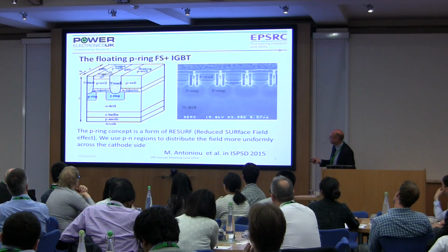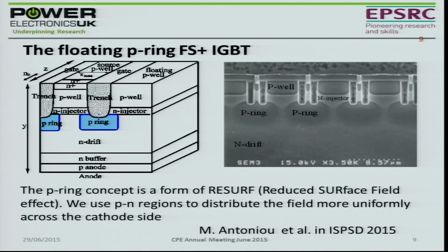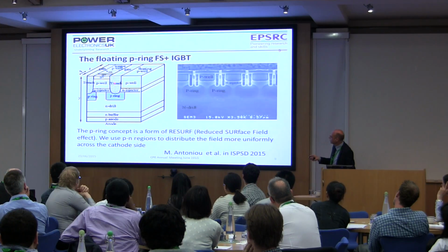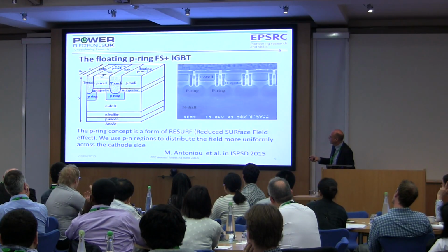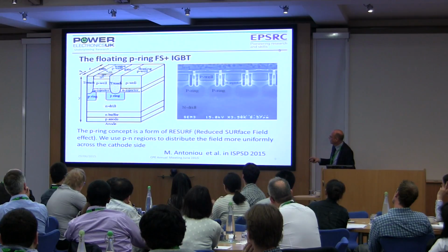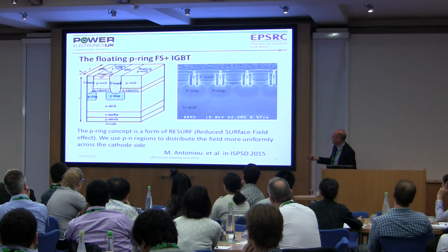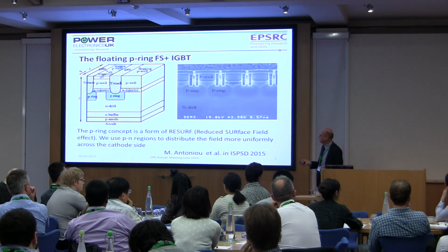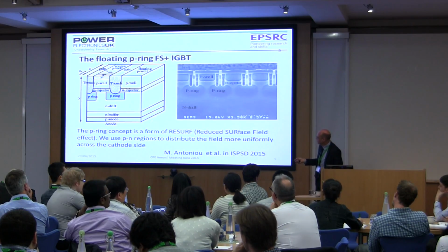So this is a trench structure with an N+ injector here. In this device, there's an oxide down the side of these trenches, which forms the sort of MOS structure. You get a channel down the side of the trench, and then this injector, so electrons would flow from the top through those inversion layers and enter this injection layer, and then be injected down here. So this oxide on the side of the trench here is what's actually doing the switching. This bottom part of the device is responsible for the voltage blocking capabilities of that structure.